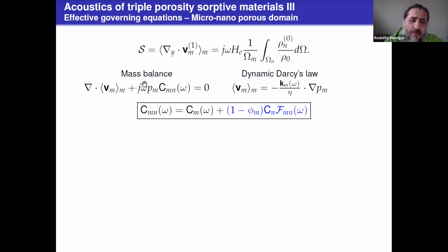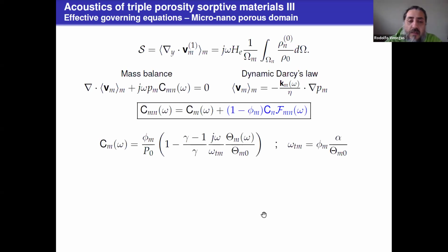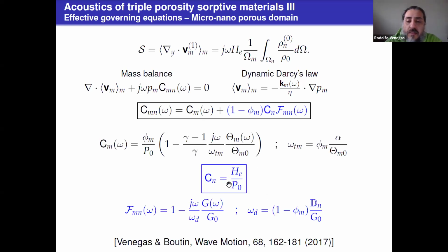And we end up with what looks like a classic macroscopic description with a mass balance equation and a dynamic Darcy's law, with the difference in blue, where Cn is the contribution of the nanopores domain compressibility, and F is a function that accounts for the interscale mass diffusion processes. So in particular, Cn is proportional to H. H is the absorption equilibrium constant, and F takes this classical form.